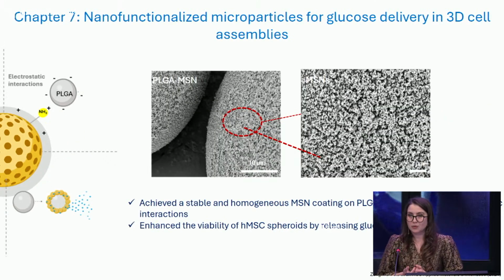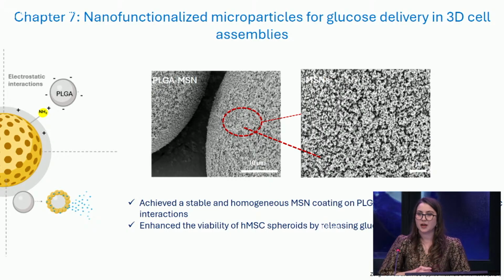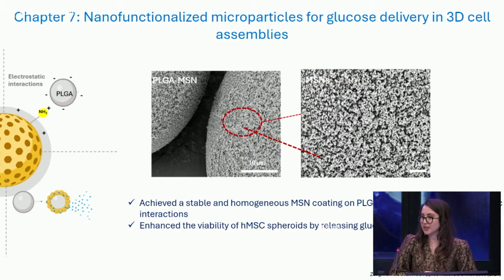Here, I first developed a novel strategy to coat negatively charged PLGA microparticles with positively charged MSNs using electrostatic interactions. This method results in a homogeneous and stable MSN coating on the PLGA surface for up to 9 days. And the next step was creating hybrid biomaterial-cell spheroids by integrating PLGA microparticles coated with glucose-loaded MSNs into human mesenchymal stem cells. So our viability assays demonstrated that glucose-loaded MSNs improve viability of spheroids, even in hypoxic conditions.